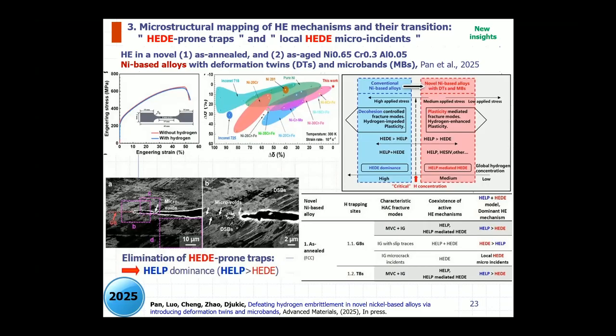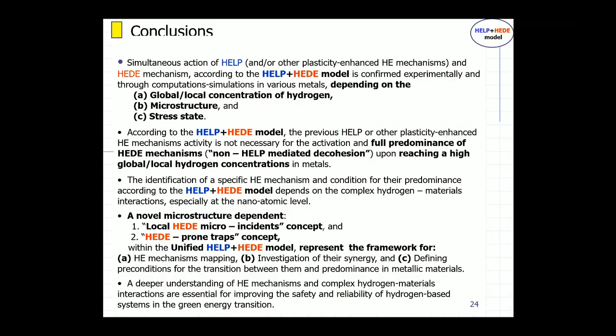So what's going on with the deformation twins, with the introduction of deformation twin and microbands? We provide the dispersion of hydrogen throughout the microstructure, so we avoid the localized hydrogen accumulation at particularly HE-prone traps. So we have a very uniform distribution of hydrogen, which means that due to results of metallurgical engineering, we provide a hydrogen embrittlement resistant new nickel-based alloy, because we all know that nickel-based alloys are very prone to hydrogen, as all high-strength alloys. So, conclusion. Global, local concentration, microstructure, and stress strain define the transition between mechanisms.